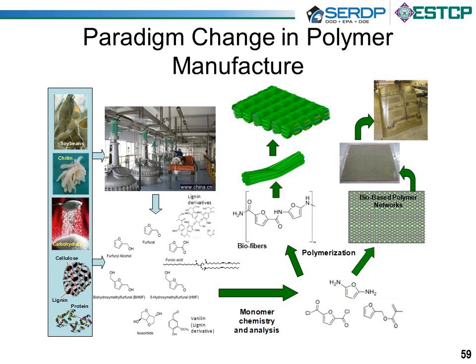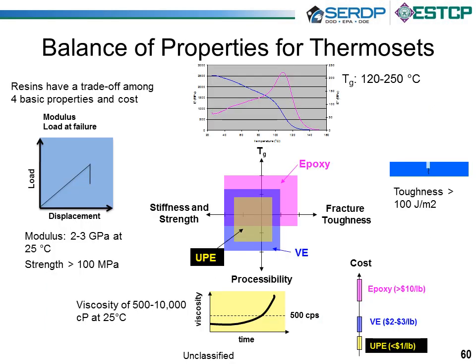Now, for thermosetting materials, which is the focus of my talk today, there's really a balance of a number of properties outside of the toxicity issues and environmental issues, which I'm going to talk about as well. But there are various important properties of these materials, including the glass transition temperature. We want a high glass transition temperature. For the Army, about 120 is mostly acceptable, but for various other high-performance applications, we want Tgs, as Ben talked about, closer to 300 degrees Celsius. We would also like to have a toughness of at least 100 joules per meter squared. We need to have a modulus over 2 gigapascals at room temperature and a strength over 100 megapascals at room temperature.